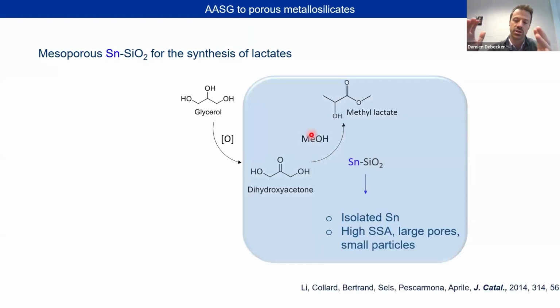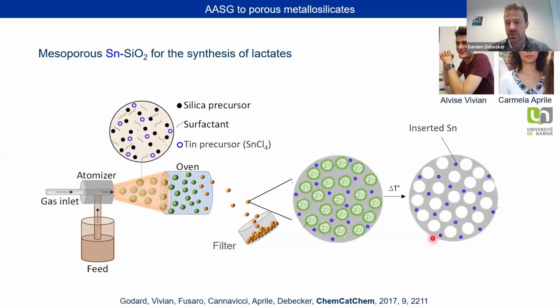If we focus on the second reaction, we know from the literature that we need tin-based catalysts and that it works better if we have really dispersed tin in the silica. Ideally, we should have high specific surface area, large pores, and small particles. So we thought our aerosol process was primed to solve this kind of challenge. And indeed, this is the same schematic as I showed you just before. We start with a solution that contains a silica precursor, a surfactant, and a tin precursor. The tin precursor is trapped in the silica matrix, and when we calcine, we hope to have this kind of particles.